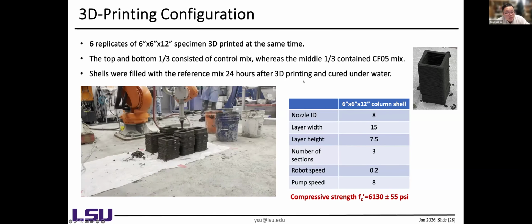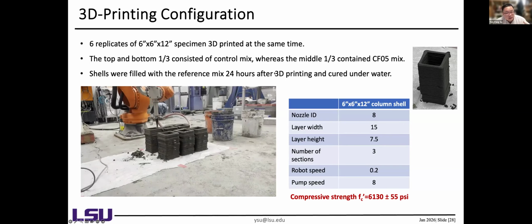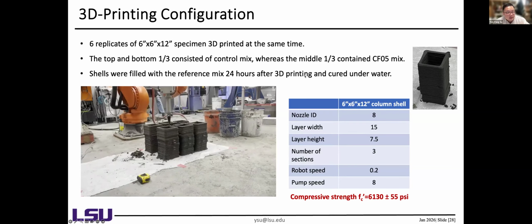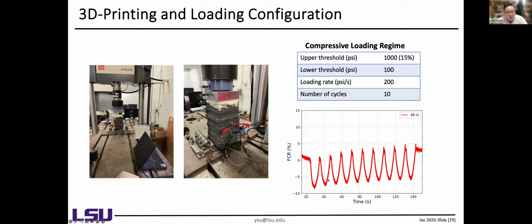For this entire structure, the top and the bottom one-third are a regular control mix, and the middle one-third is the CF0.5 mix, and we also tested its 28-day strength, and the strength is not bad. It's around 6 KSI. We then conducted this self-sensing evaluation with around 15% of the load rate, and we can successfully obtain this change to reflect the cyclic loading.